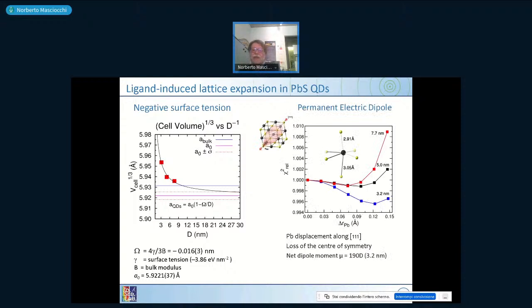Now you can see here that the structural distortion is shifting the lead atom, which is the most highly scattering, away from the original cubic position. And you can see again that if you go to different sizes, the 3.2 nanometers is more distorted. You have 0.12 angstroms away. If you go to the intermediate one, the distortion is smaller. And if you go to the larger crystal, the distortion is less pronounced. It's only half of what it was before. Again, if you go to larger nanocrystals, you have a number which approaches 0, so the structure is really cubic.